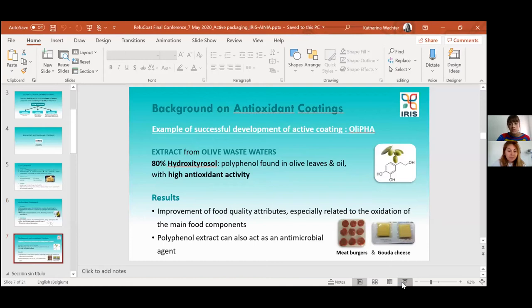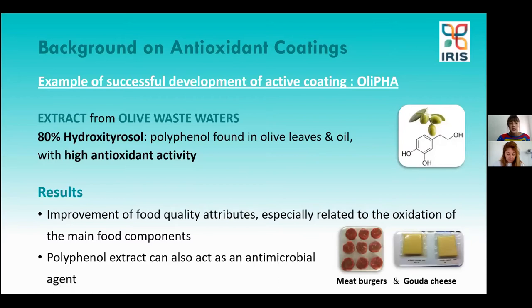In our research group, we already have a background in antioxidant coatings. As an example, I will speak about OliPHA, which used an extract obtained from olive waste waters and contained 80% hydroxytyrosol, a type of polyphenol found in olive leaves and oil with high antioxidant activity. The polyphenol coatings led to improved food quality attributes during storage compared with non-active packaging, especially a decrease in oxidation values for meat burgers and Gouda cheese.